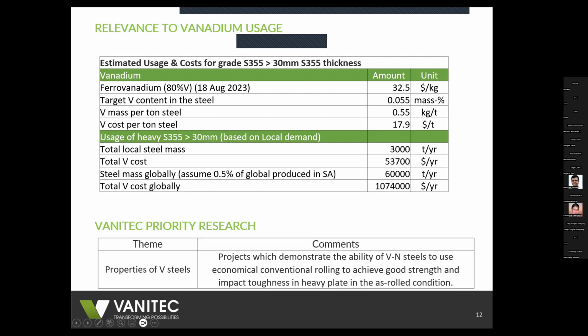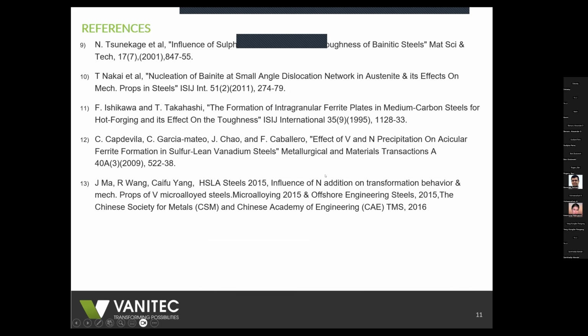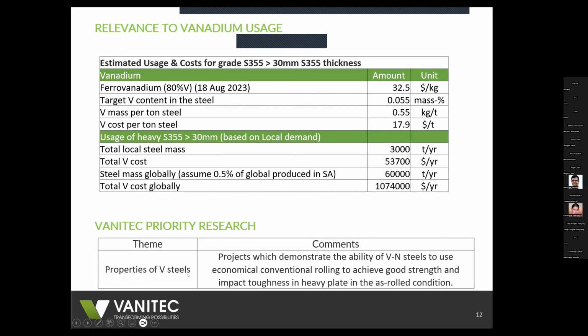Then relevance to the vanadium usage, these are typical costs of ferrovanadium, vanadium masses per ton, and our local demand would be so much, and then global potential vanadium or estimated vanadium vanadium cost globally for this would be over $1 million. Where this fits in with the vanadium research is to demonstrate the ability of vanadium nitrogen steels to use economical conventional rolling to achieve good strength and toughness in heavy plate in the as-rolled condition.